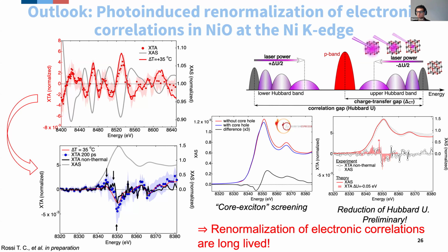So it should in principle be broadened by the experimental resolution, but I think it's still pretty convincing that the renormalization of the correlation gap actually does reproduce positive signals at the rising edge and the negative signal that you see at the white line. And on top of that, this 50 millielectron volts renormalization of the electronic correlations is what has been observed by others in recent experiments that were done at the XFEL. So overall, the message is that using this pump probe spectroscopy, we are able to see a renormalization of electronic correlations.